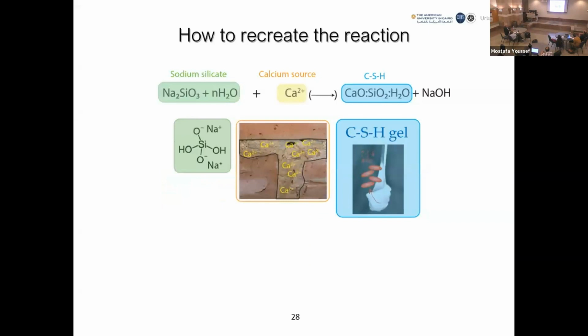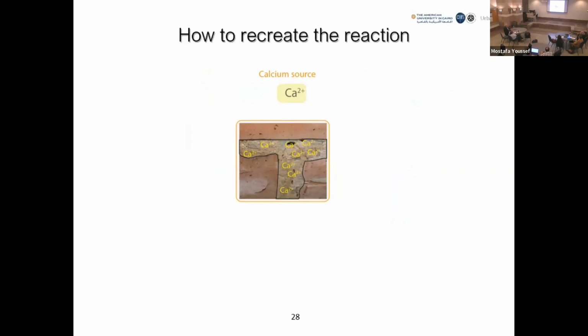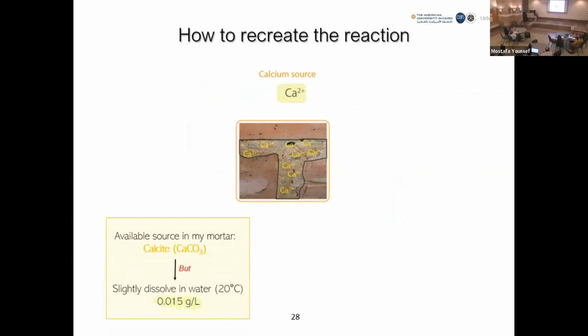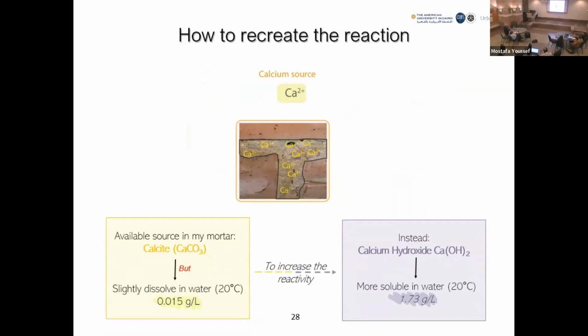This again is the reaction that I talked about before, and I would like to focus your attention for a second on the calcium source. Now we are sure that in my material I have calcium because I have calcite, but where is the problem? The problem is that calcite in water solution dissolves in a very slow way, and so I would like to have something that permits me to work with this reaction in a faster way. So what I did is add a small quantity of calcium hydroxide. How did I add this kind of material?